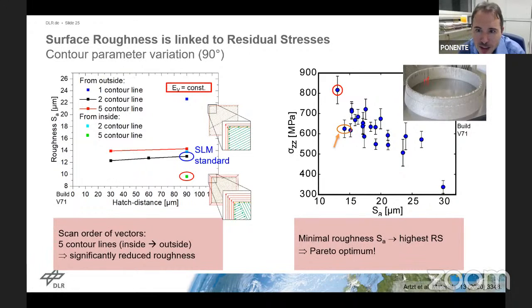The catch-22 in this case is you don't only affect the surface quality, you also affect the residual stresses. And we did that with measurements at the synchrotron BESSY in Berlin for different specimens that have very different surface scan strategies and scan parameters that result in very different surface qualities. And you can roughly see that a surface that has a very high roughness here at around 30 micron will lead to very low surface residual stresses in this case, stresses in build direction. Yes, very low surface residual stresses means you don't get cracking of your part.